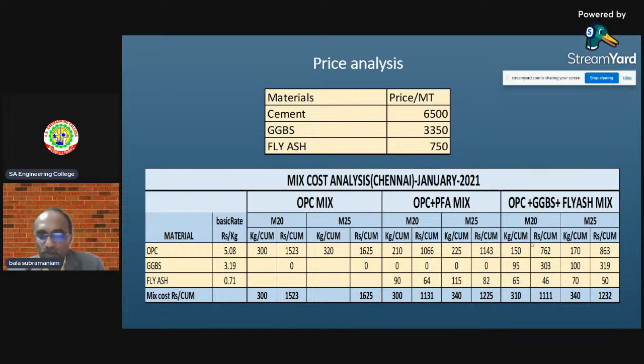That could use 150 kg of cement, 95 kg of GGBS, and 65 kg of fly ash put together. So now here, for a customer who wants OPC and buys OPC at 1,523, will I be able to sell this 1,111 to him easily? There is a big difference. What is the difference? 1,523 minus 1,131 is huge, right? Close to 350 rupees. It's a huge difference.